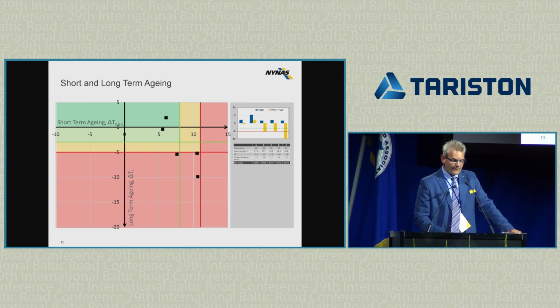On the y-axis, I've given the delta TC, whereby anything above minus 3 is okay. Anything between minus 3 and minus 5, there's a risk of cracking. And anything that is below minus 5, there is a serious risk of cracking. These are the 5 bitumens that we've tested. And you can see they all meet the short-term aging test, but you can see already there's a difference in terms of delta TC, and therefore would expect a difference in long-term aging behavior.